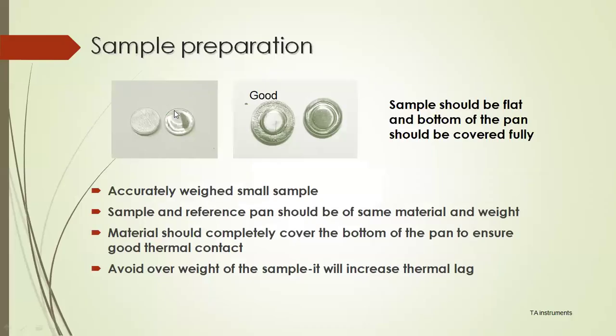This is how an aluminum sample pan looks. You take a sample pan and weigh it. I strongly suggest that even though the sample pans come from the same box, you keep one sample pan with the lid as the reference and one for the sample. But the reference pan and the sample pan where you are actually weighing your sample should be of the same weight, because in DSC you are measuring heat, which is joules per gram. So the weights of both pans should be absolutely similar, and the samples accurately weighed.